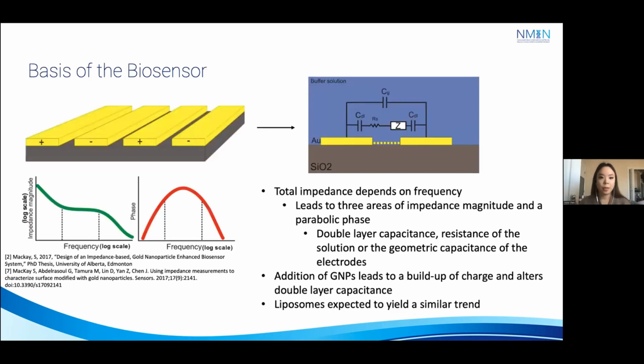So the basis of the biosensor then relies on electrical impedance spectroscopy, and impedance and phase both depend on frequency, and a characteristic impedance curve has 3 distinct areas and a parabolic phase. And the impedance curve can be divided into 3 sections, the first being dominated by double layer capacitance, the second being dominated by the resistance of the solution, and the third being dominated by the geometric capacitance of the electrodes, which can be seen in the equivalent circuit on the top right.